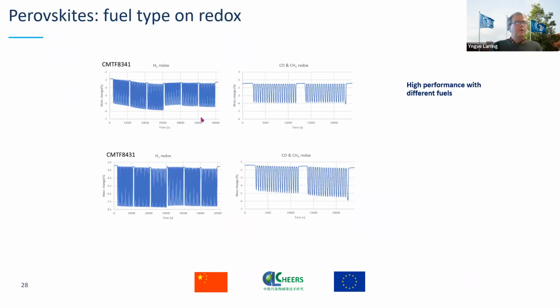The perovskite type, we have the 8341 and 8431, both react very nicely with the methane, CO, and hydrogen. The methane reaction should, of course, be wished to be slightly better, but sufficient, most likely.